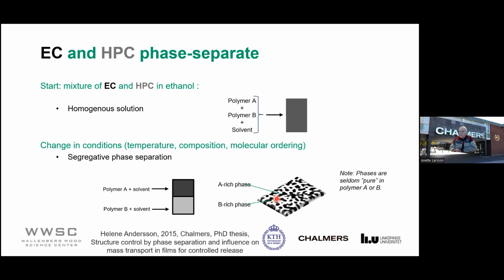And these molecules of A are then transported to this A-rich phase. When we talk about diffusion, normally we say that you have a high concentration and then it goes to the low concentration regions. That was what we saw before. But here we have a situation where the thermodynamics rules everything. So we actually have uphill diffusion, where it goes from low concentration to high concentration of the A phase, which is a little bit funny.